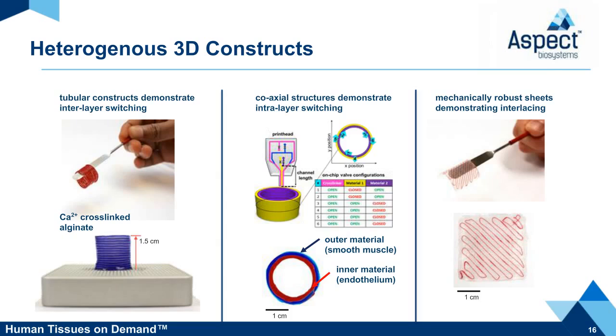In the center, we show that with on-the-fly computer coordination of on-chip processes within the printer toolpath, we can create co-axial structures with clean boundaries and demonstrate coordinated intra-layer material switching. This structure can be used to model the various concentric layers of a tissue like a blood vessel or the intestine. On the right-hand side, we demonstrate interweaving one hydrogel within a solid and thin film of a second hydrogel. This capability can be used as the basis of a vascularized skin or tissue patch. These structures reproduce the intended geometry with high fidelity and are mechanically robust post-printing.